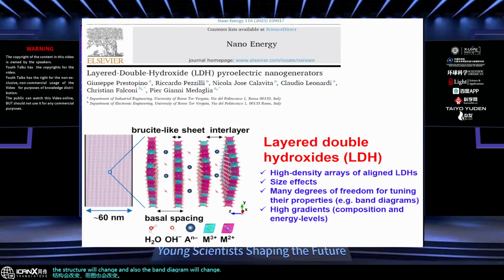And how will it change? So the way you can model is by performing single atomic level simulations, which of course is quite complex. And in fact, your results will depend on the specific choices of the divalent metal cation, the trivalent cation, the anion, and their composition. So, for instance, the divalent to trivalent cation ratio.